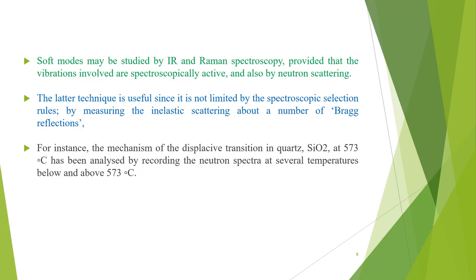The latter technique is useful since it is not limited by the spectroscopic selection rules. So by measuring the inelastic scattering about a number of Bragg reflections, the atomic displacements that are responsible for the soft mode and the phase transition may be determined.